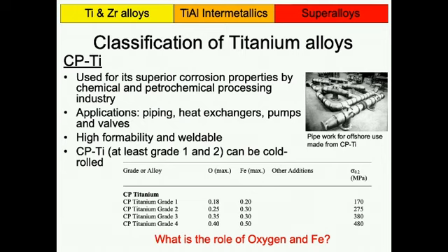You can see that depending on those grades, you have different oxygen content. Please don't think you have to learn now what the oxygen content of these different grades is. Just remember that there are different CP titanium grades, and that in principle they become stronger with increasing grade, and it might be worth remembering that essentially the strength comes from increasing oxygen content, right?